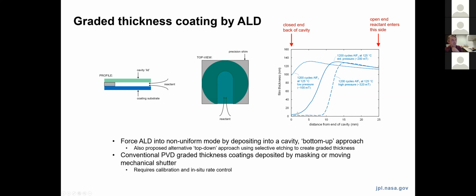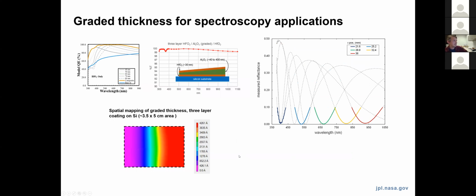For a fixed cavity, of course, you would be fixed with the given profile based on the geometry, but it turns out you can tune this profile essentially by tuning the working pressure of the process to get either further or not as far into the cavity, and then build up whatever slope or linear profile you want by superposition of these different ALD cycles at different pressures. Of course, there are ways to create these graded thickness coatings by other thin film techniques, for line of sight techniques like evaporation and sputtering. You can do this by masking or shuttering. But we think maybe there are some advantages to this approach as well, since it doesn't require these moving parts in your vacuum coating chamber.